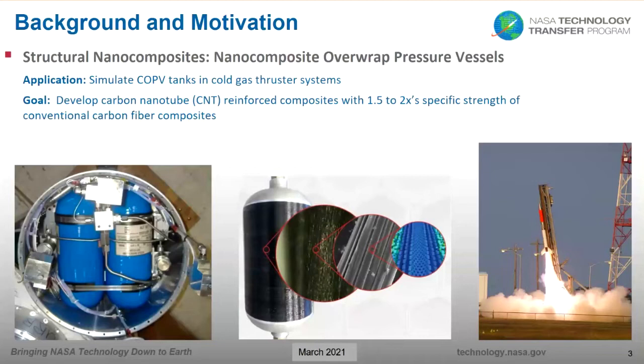Eventually our material supplier ended up developing a very strong carbon nanotube yarn material, which is the material that we stuck with for the duration of the project. I'm showing that in this middle image here. We actually saw this project from its infancy, from identifying likely nanomaterial candidates that would make a good overwrap material, to performing coupon level fabrication and testing of the nanocomposite overwrap that we eventually developed. Then we went on to wrapping the tanks with the nanocomposite overwrap, and finally completing this project with the flight test and demonstration in 2016.